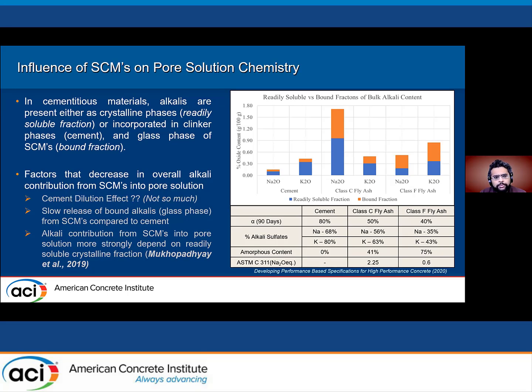So when we look at the factors why SCMs contribute to a lower alkali pore solution, one of the common aspects is the cement dilution effect. But you see in the graphs on the right, this would not always be true. If you replace an equal amount of cement with even class F fly ash, the one that we used in our project, it definitely has higher alkalis compared to the cement, and class C had significantly higher. So the cement dilution effect for fly ashes has to be considered with a little bit more caution.